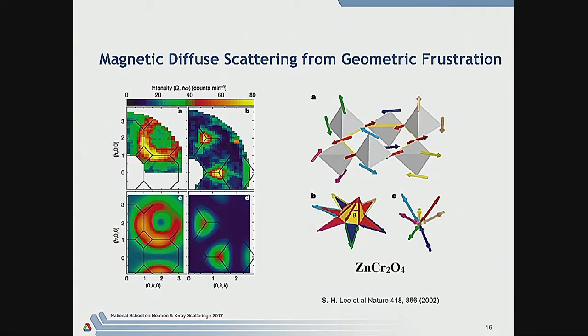One of the things about these materials is they're frustrated because the spins can't, if they have, say, antiferromagnetic interactions, you can't simultaneously satisfy them all on the vertices of a tetrahedron. But what's interesting is that they actually get, in this case, what are called spin protectorates. So you can see this spin here, and this spin, this red one, this one, et cetera here. I don't know if you can tell from this diagram, but you can actually rotate all of these spins without affecting any of the interactions of the other spins around. So in other words, they're free to rotate together in what Sung-Hun Lee called a spin protectorate. And that gives rise to this beautiful diffuse scattering, which is characteristic of that collective motion of just a small cluster of ions.